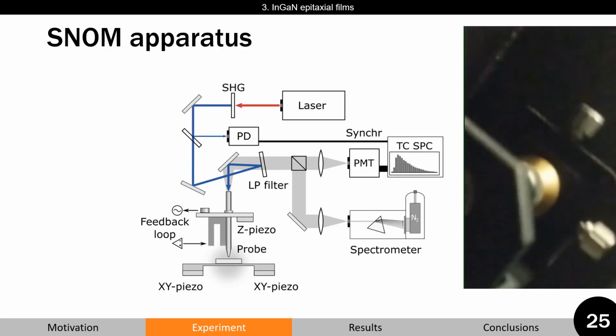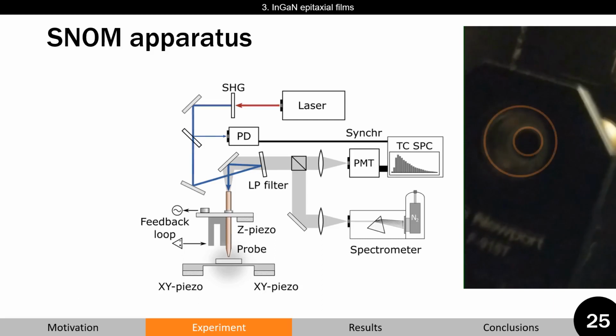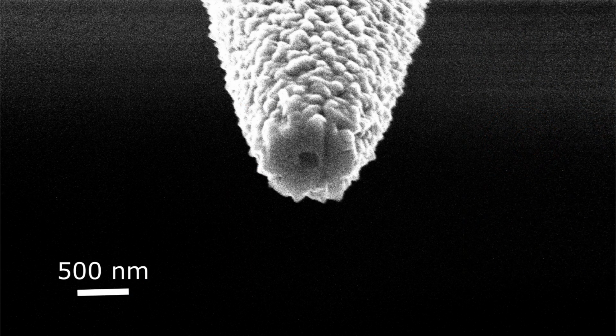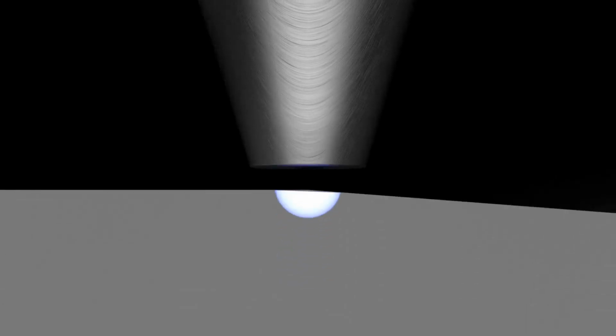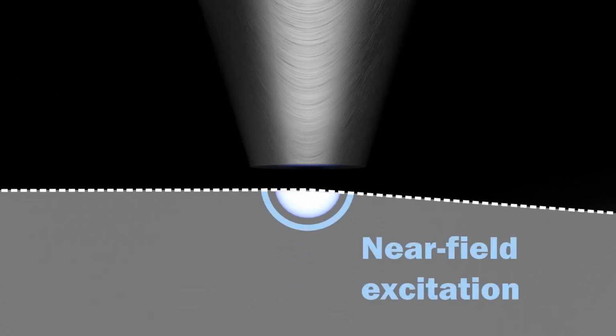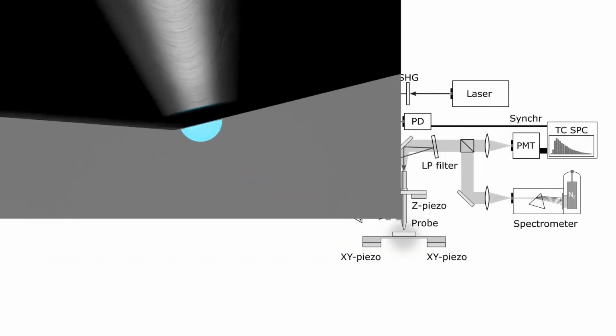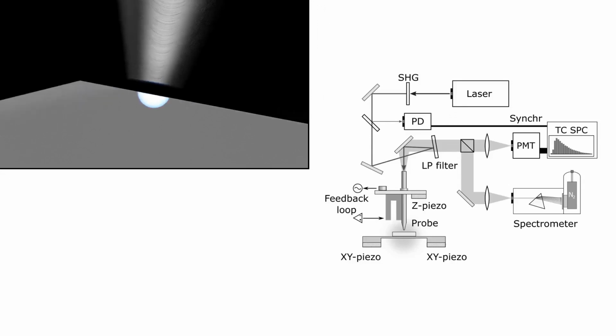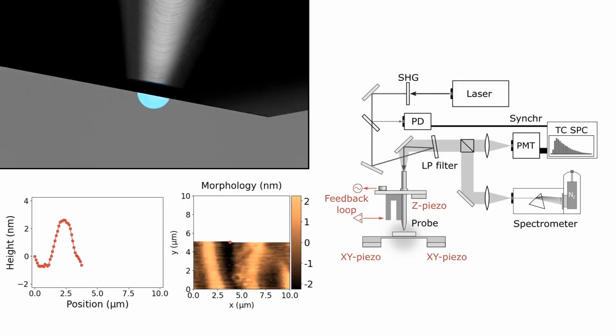At the other end of the fiber, we have a metal-coated probe. Here is a SEM image of a typical metal-coated scanning near-field optical microscopy (SNOM) probe. One can observe a sub-wavelength aperture. This probe is positioned in close proximity to the sample, where near-field excitation can be generated. Using a feedback loop, the probe-to-sample distance is controlled, which allows us to measure the morphology.